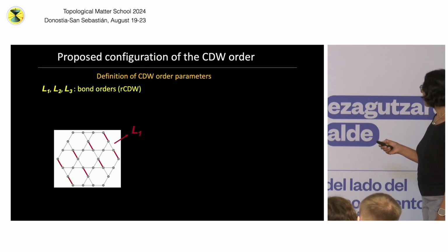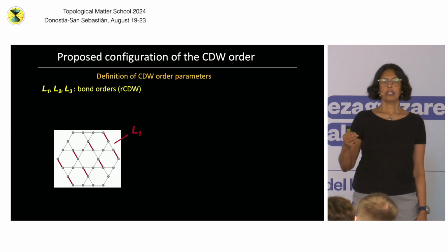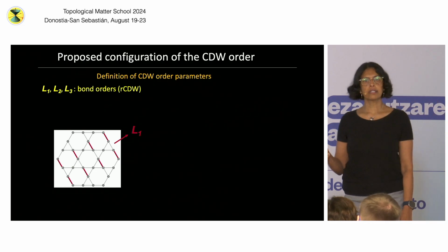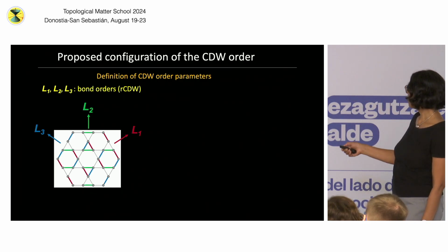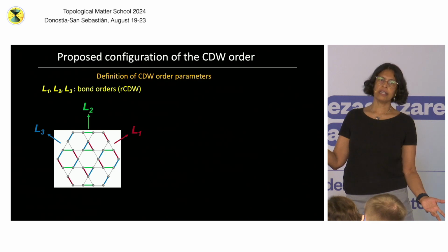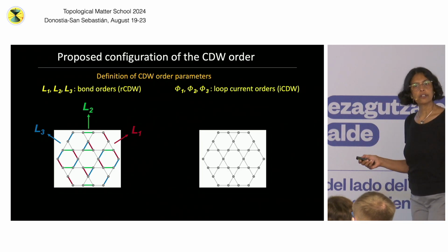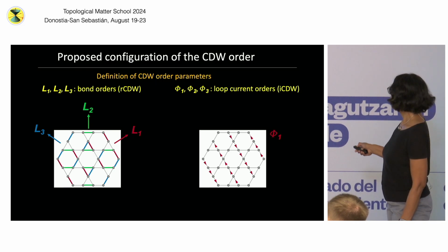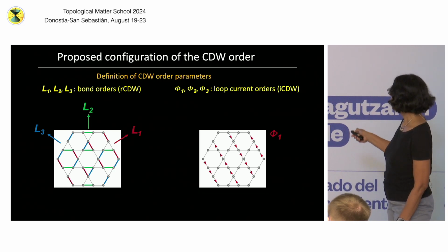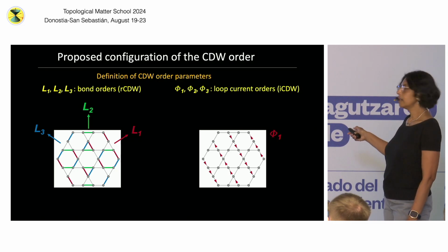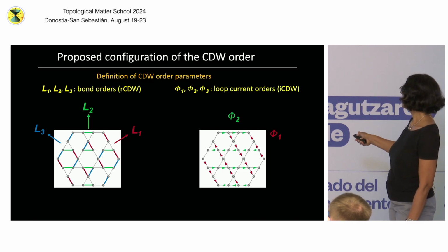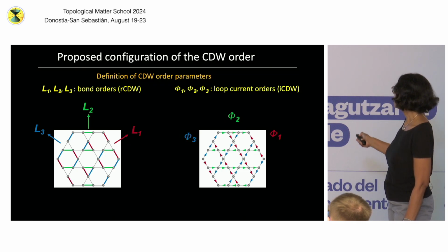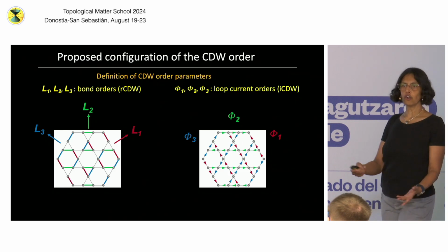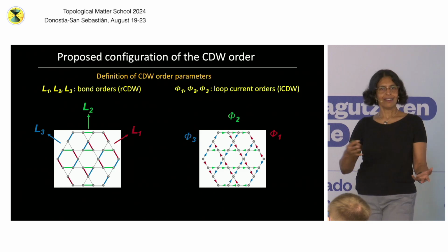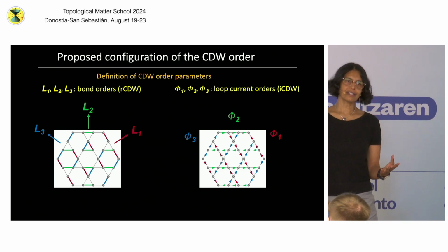But what really is happening in the system is that there are two kinds of orders. There's a bond order that Stephen Wilson was telling you about, in three different directions. That's this one, and you can think of it as the regular CDW order. There's also a loop current order. Here you have spontaneous loop currents going in three different directions. For example, this would be one of the order parameters. Here you have currents going this way, this way, this way, this way. Then you have the second order parameter, current going this way, this way, this way, this way. And then the third order parameter, three loop currents, right? They don't look loopy. They're going in one direction, but they're still currents. Any spontaneous current means broken time reversal symmetry.